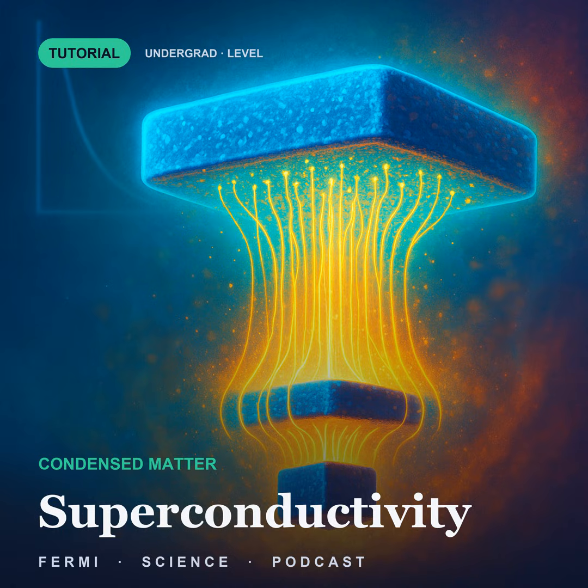A current pushes sideways on the flux lines. If they move, they dissipate, and your zero resistance is gone. Pin them, and the current flows up to the field, where the pinning gives way. Niobium titanium carries the 8 1/3 Tesla dipoles of the Large Hadron Collider against 8/100ths of a Tesla for lead. You have used the phrase, the charge of whatever carries the phase, twice now, without saying what it is, and I think that is deliberate. Entirely deliberate, because it is measurable, and the measurement settles the microscopic question without mentioning phonons, gaps, or Bardeen.